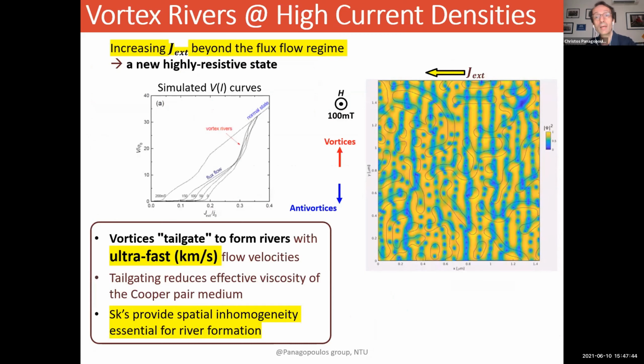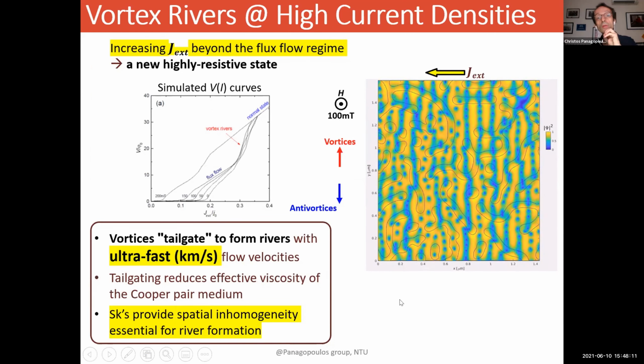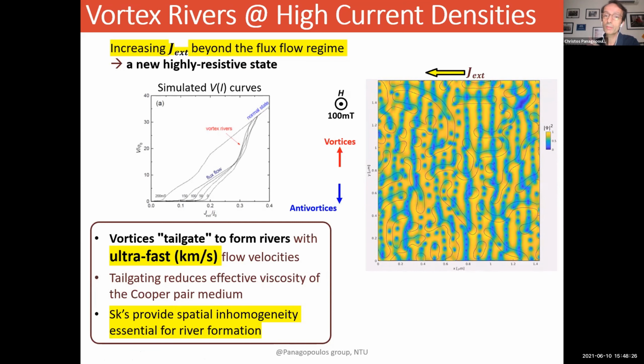You can look also at what I mentioned earlier, that in principle there was some theoretical work years ago predicting that vortex rivers and high current density, in the presence of coupling between superconducting vortices and antivortices with magnetic skyrmions, would increase the speed or the velocities of vortices in the superconductor. Indeed, what we find is that vortices tailgate to form rivers with ultra-fast flow velocities. In fact, the velocities of these rivers in the superconductor go to kilometers per second, which is really fast. And the tailgating reduces the effective viscosity of the Cooper pair, the superconducting pair medium.